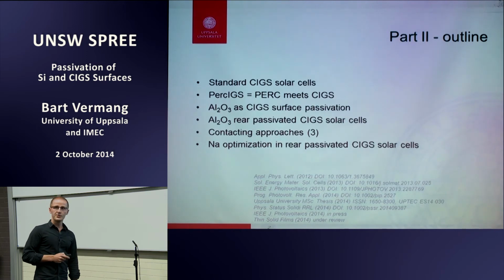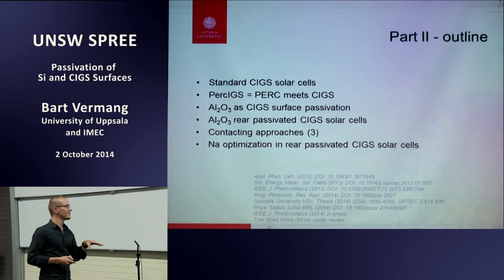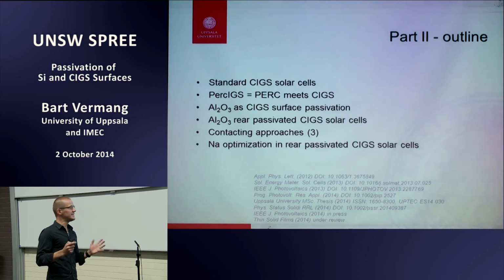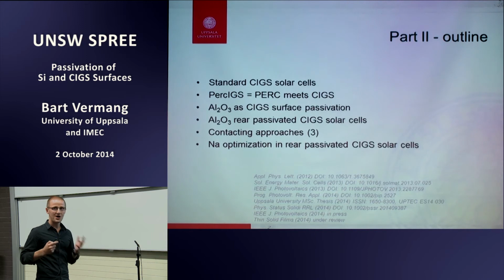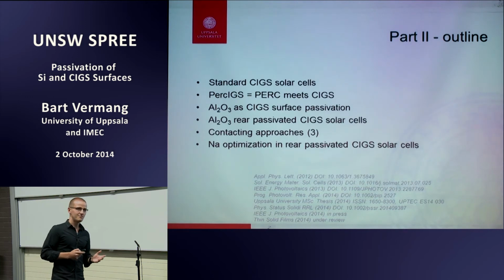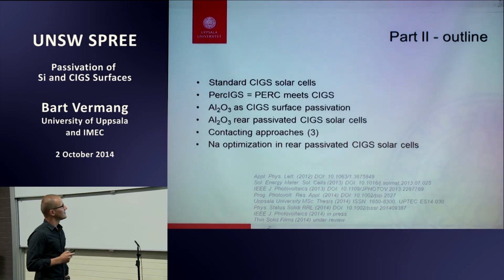Also here we're using aluminum oxides, for a few reasons. I tried a few other layers before, but what we do here is grow the CIGS layer on top of the aluminum oxide layer, or on top of the passivation layer. If you use a layer that is not that rigid, you just lose it. It is in a selenium atmosphere, so it's quite harsh. We have been using, for example, cadmium sulfide in the past, or zinc sulfide. We just lost those layers.